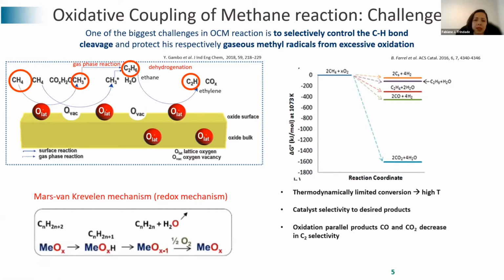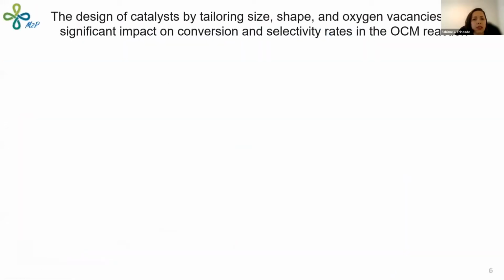I can list here a lot of challenges involved in this reaction. As I said, it's still not commercialized. The biggest limitation of this reaction, the biggest challenge that we still study very hard to overcome, is that the first part, the activation of methane to produce methyl radicals, is more favored to form CO and CO2 products. So this part is very important: the catalyst needs to be very selective and control this oxidation to form the desired product, ethylene. To overcome this challenge, we propose to design a catalyst by controlling the morphology, oxygen vacancies, and disorder to improve the OCM reaction.